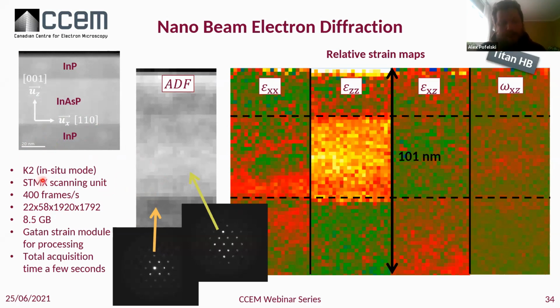Just a couple of numbers to make you realize how big this data is. I couldn't do the binning easily in this type of settings, so I just took the full CCD here. You see the number of pixels is huge, while the map is relatively small, and this is already 8 gigabytes of data. There is definitely some improvement to do here, spending some time. And I used here the Gatan strain module processing, which uses a center of mass approach. Since it's not open source, I don't have exactly all the details, but this is what I've been told. And the total acquisition time for the entire map is actually a few seconds. It's amazing how fast this goes and how fast you can generate gigabytes.